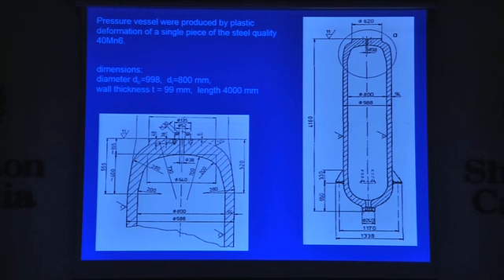This is actually the air vessel, which was used for a quenching machine with 1,000 tons of pressure power. It was built 70 years ago, and it was in service for about 50 years. During the inspection, they found cracks, and the idea was to see what is happening in this material.